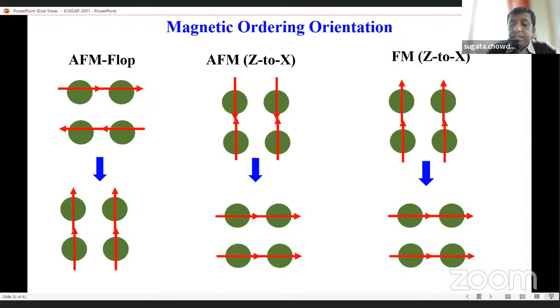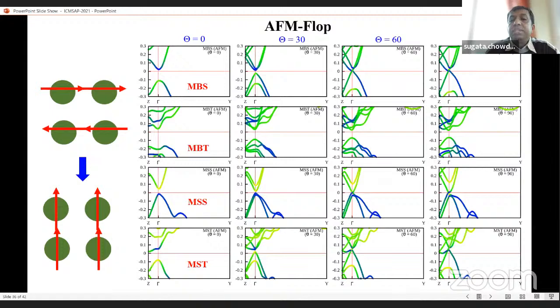We got a very interesting result here. We found that the manganese bismuth selenide structure, when it flops from the antiferromagnetic system to the ferromagnetic system out of plane, is a Weyl node, which was already shown. But the MBT is a non-trivial insulator throughout if we change the magnetic field direction.